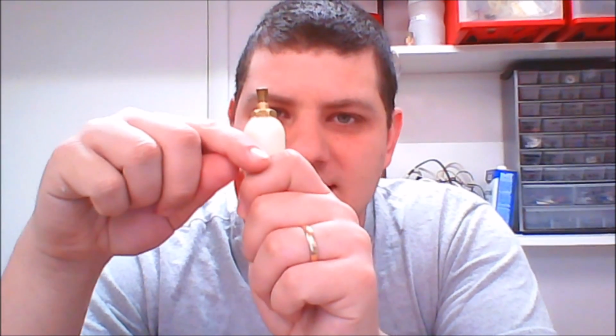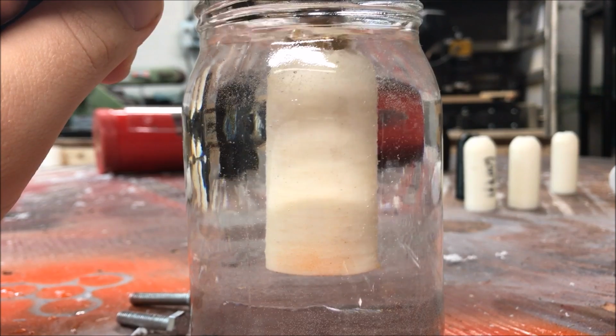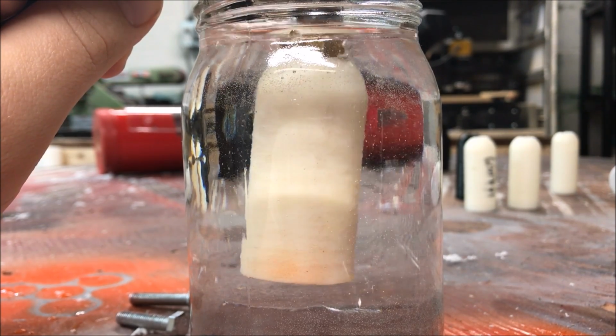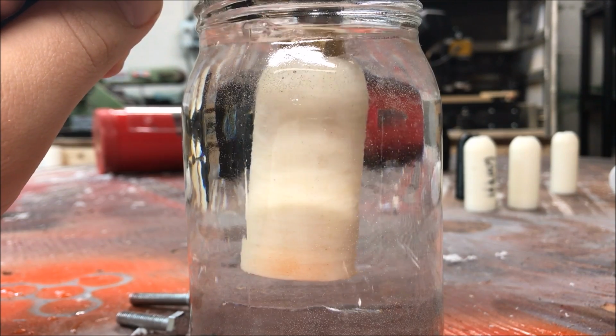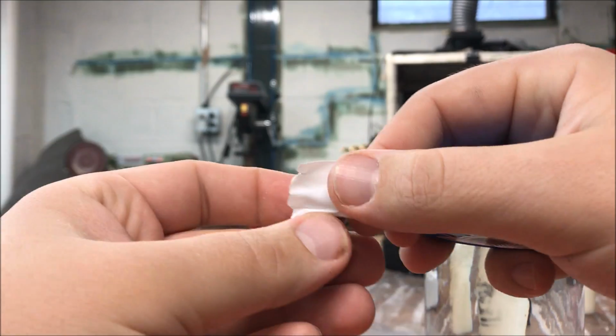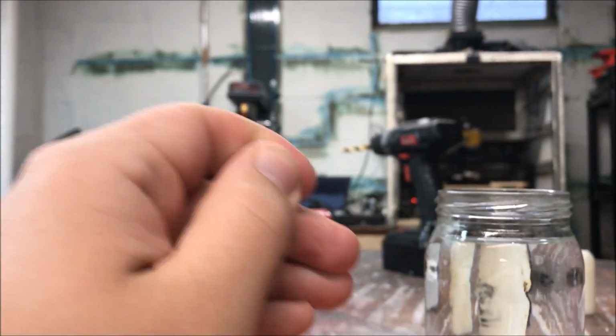The one that I sealed with the fiberglass resin actually did not leak through the plastic whatsoever. The only place it leaked was from where the brass attachment here met the plastic. It's actually a good thing because it meant that it was a problem with something that I did that's fixable and not a problem with the material. I went back and added some Teflon thread tape to the threads of the brass adapter here, and tried it again and it was sealing much better.